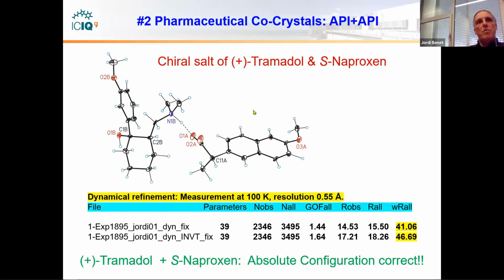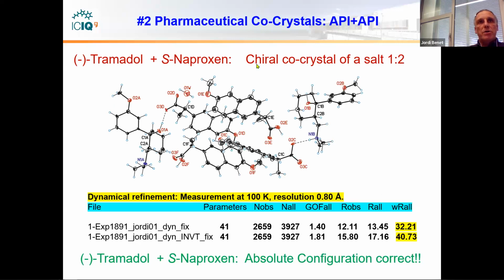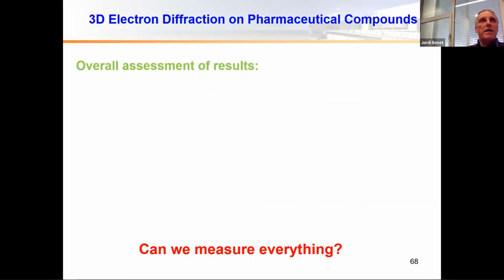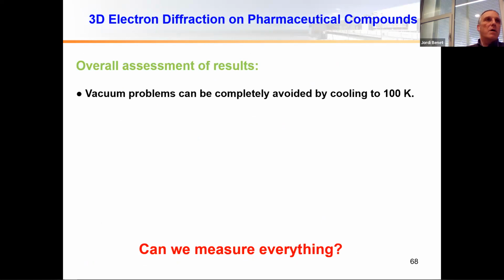But we also did the dynamical refinement on all these chiral molecules I showed before. And so you can see here in this salt from tramadol and S-naproxen, we could see the absolute configuration correctly and with a huge difference in the R values. Also in this molecule where we were not able to get absolute structure determination, we could get it with a very big difference using dynamical refinement. See, the difference is close to 8% in wR value. So this would be my last example and last explanation of all these compounds and molecules. And now let's see what our results say.